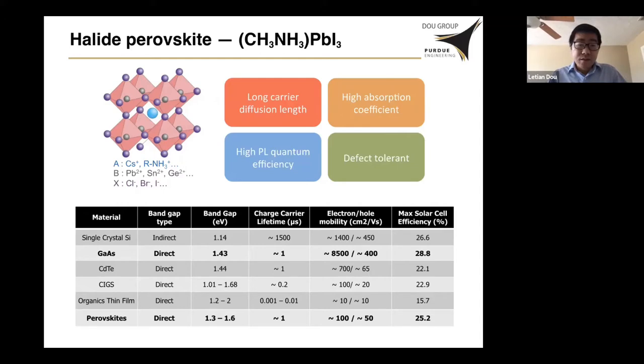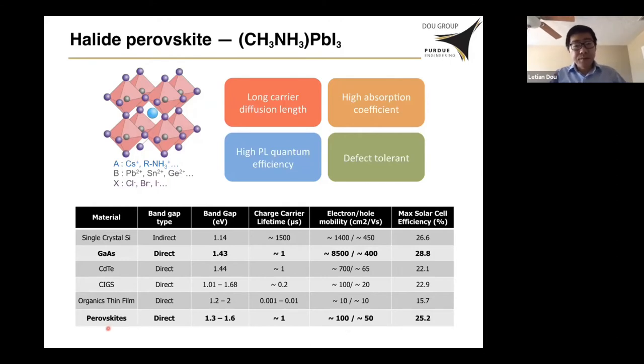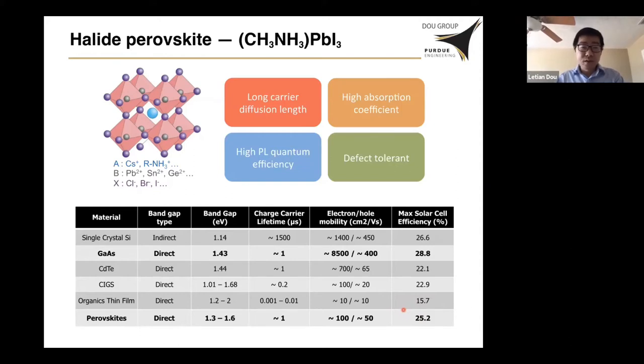Here I compare several parameters for several types of materials. I use solar cell efficiency to represent the quality of the materials. You can see that for halide perovskite, the power conversion efficiency of a solar cell has already reached 25%, which is very close to single-crystal silicon. But remember, these materials are processed using solution processing, and the device performance was achieved using a polycrystalline thin film. You cannot achieve such high performance using silicon or gallium arsenide unless you make extremely pure, very high quality single-crystal wafers. This data shows that halide perovskite is really promising in terms of high performance and low processing costs.